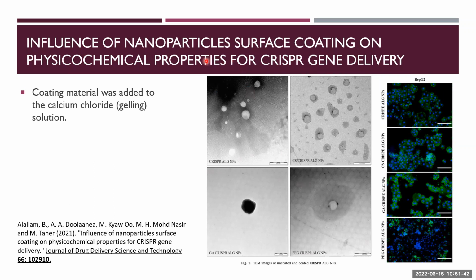So we went to do some coating of the particles. The coating was quite simple, by adding the coating material into the calcium chloride solution. We used different coating materials. We have tried chitosan, polyethylene glycol, and Arabic gum, acacia. You can see in some images the coating is quite clear under the TEM, like here.